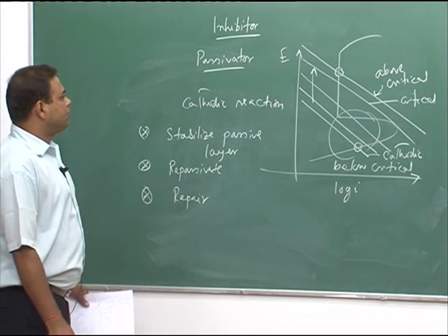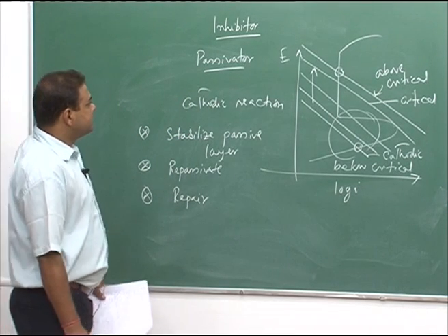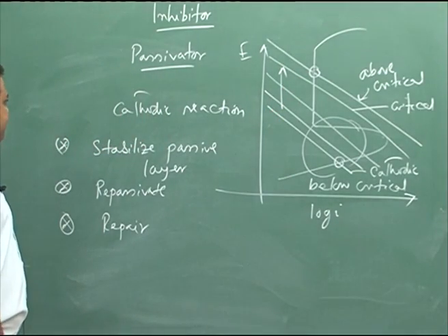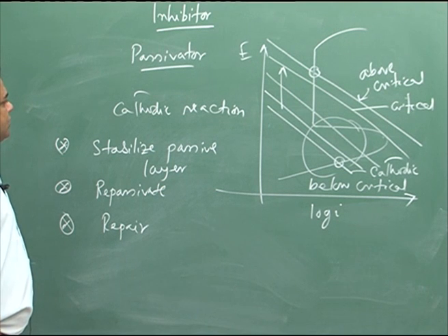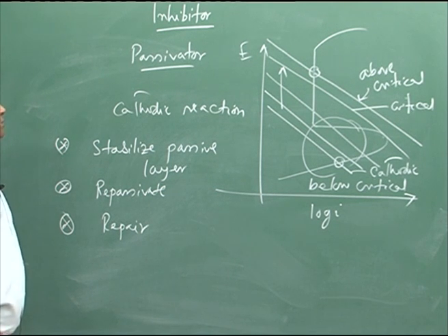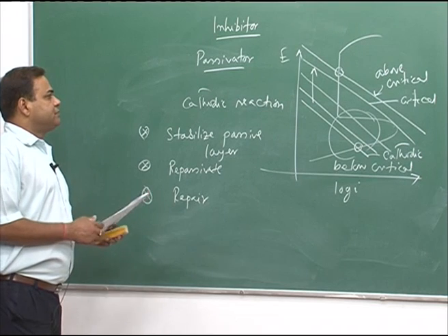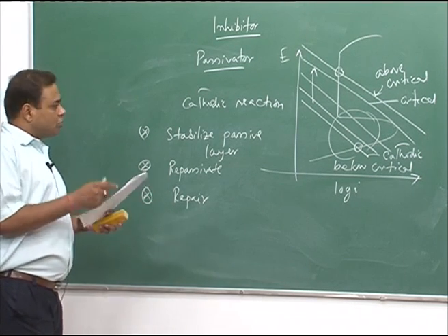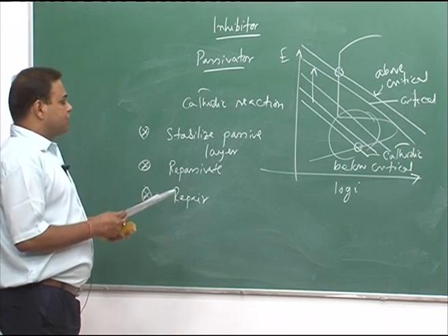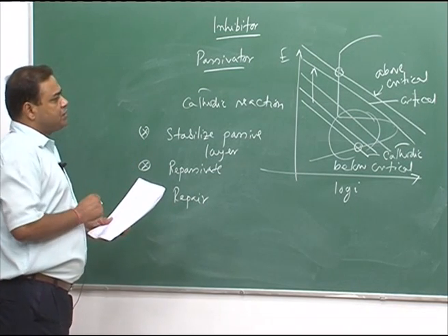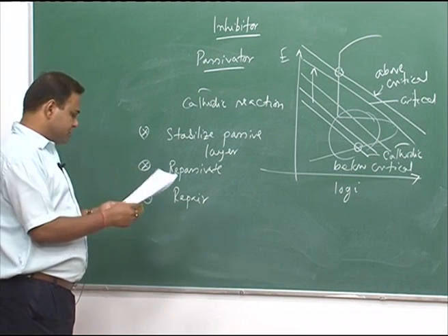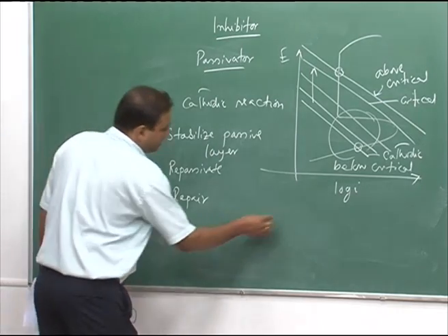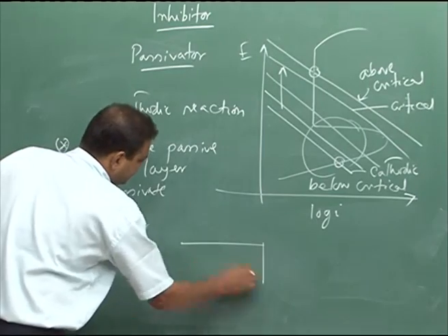the critical amount that is needed to maintain the passive current density all the time, and the critical amount would depend on whether the temperature is increasing. If the temperature increases, critical amount would also increase, and also if you have the lowering in pH, critical amount would also increase. So, those are the cases, and then of course, let us say you have this particular metal